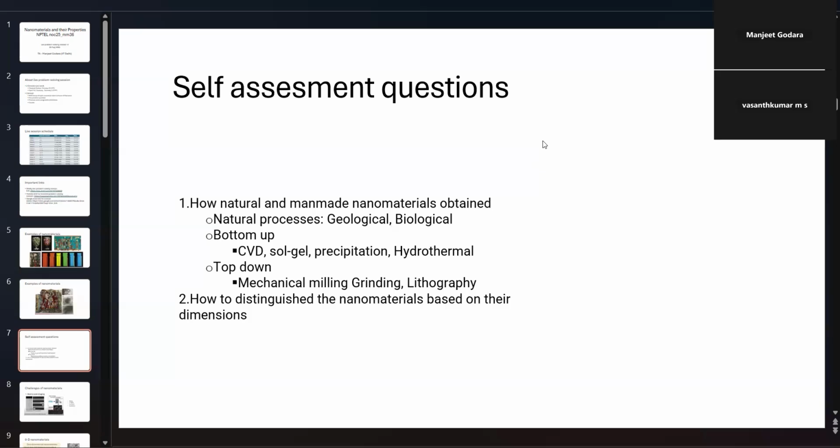And if you want to go down to nanometer, they usually use wet ball milling, because in the dry state the temperature increases a lot, and if the temperature is too high, those nanometer particles would agglomerate together and form micron size particles again. They won't go into nanometer scale. So you need liquid. They are usually made in wet mills to lower the temperatures.